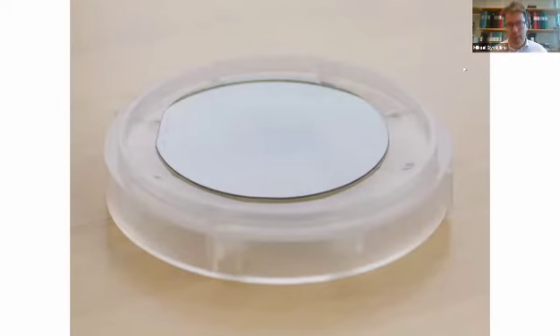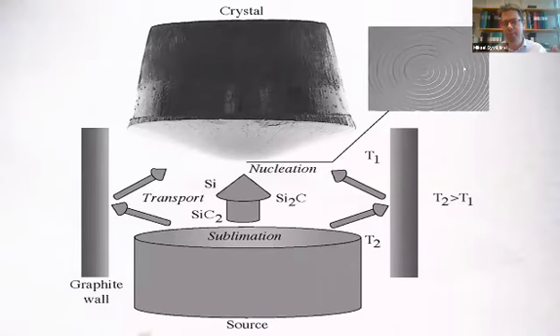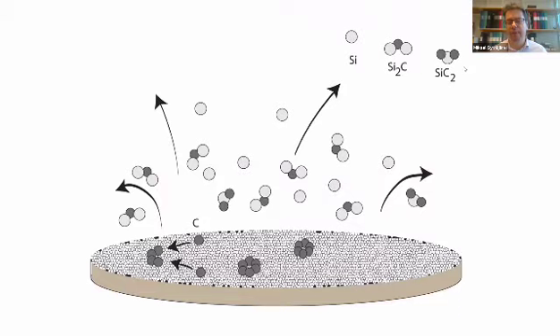The good thing about silicon carbide is that you have wafers which are available in large area. Today you can buy 6-inch diameter wafers. This is a natural process of the PVT growth and the vapor species which are formed when we heat up the silicon carbide. In the case of growth, we do this intentionally, but we can also use this to fabricate graphene. So here is an example. When we heat up the silicon carbide, you can actually get more silicon to leave the surface than the carbon of the silicon carbide wafer. So that is one way to get graphene from the silicon carbide, and the silicon carbide is the source and substrate at the same time.